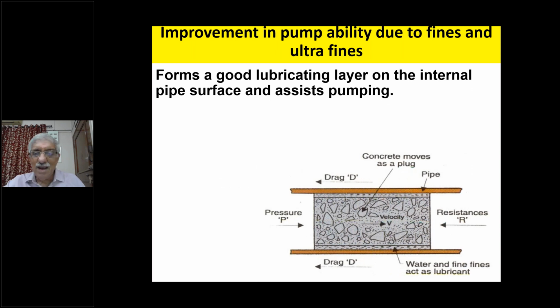It forms a good lubricating layer on the internal pipe surface. Imagine you are squeezing the concrete while you are pumping. The pressure is applied from behind by the pump, and the resistance is offered by the roughness of the pipe. So the concrete gets squeezed, and when you squeeze anything, what comes out? The paste. The paste comes out on the internal surface of the pipe and lubricates the pipe. Therefore, it is very important that fine and ultra fine material is used. It improves the lubrication layer, and therefore the pump does the pumping without any difficulty.